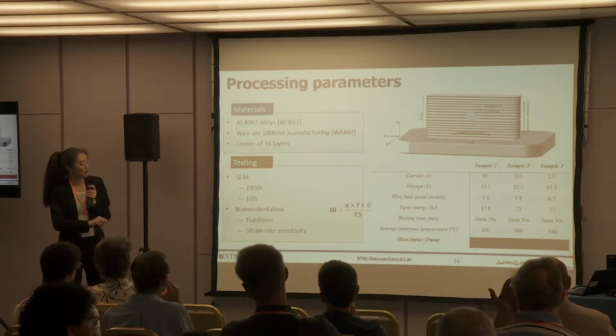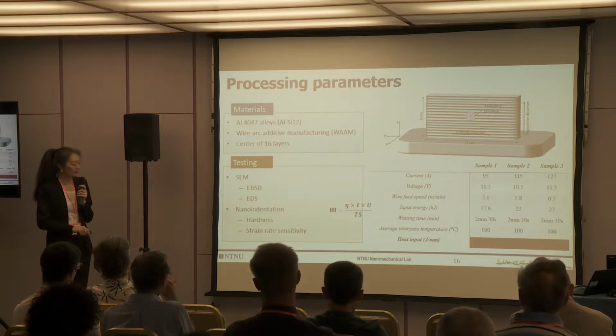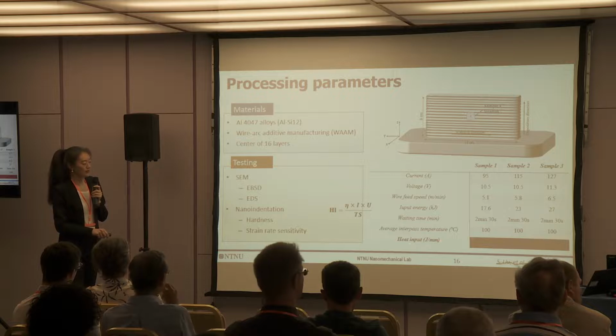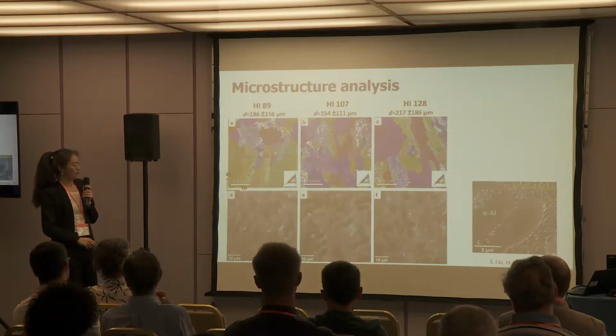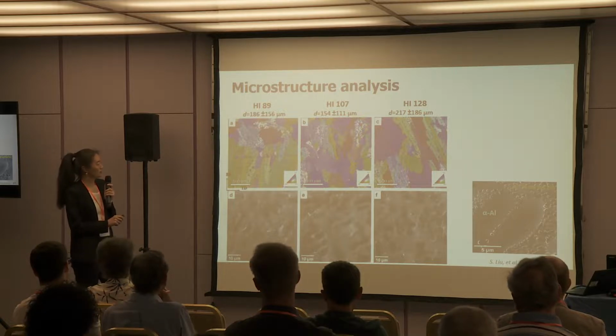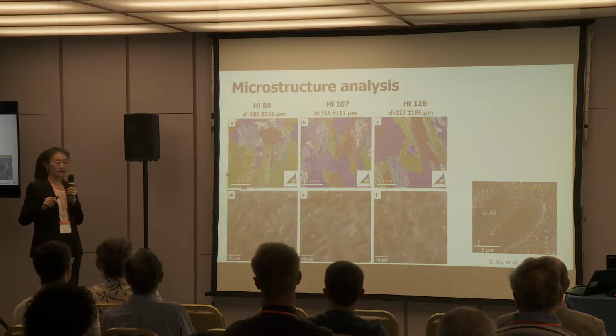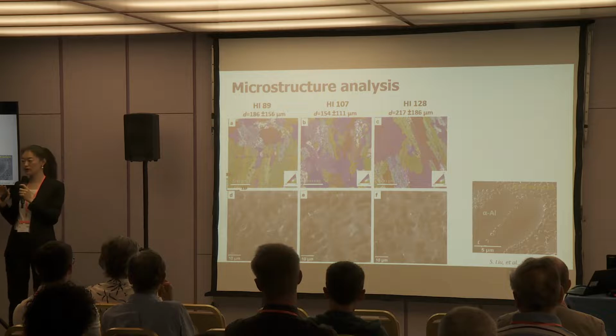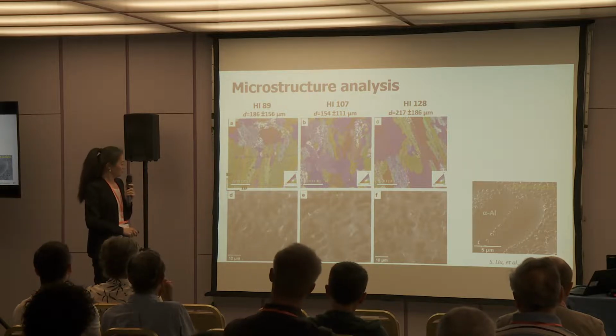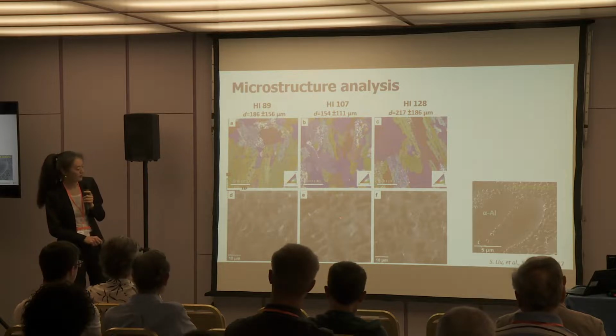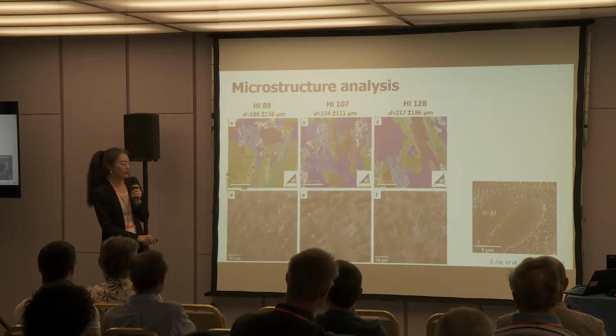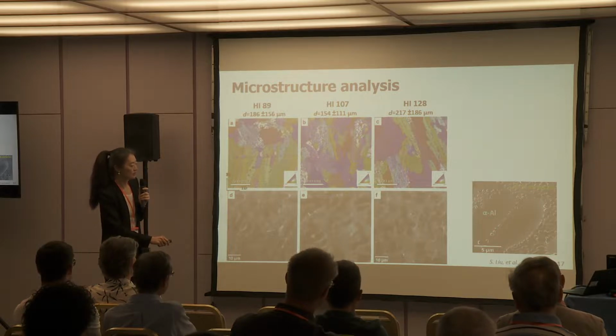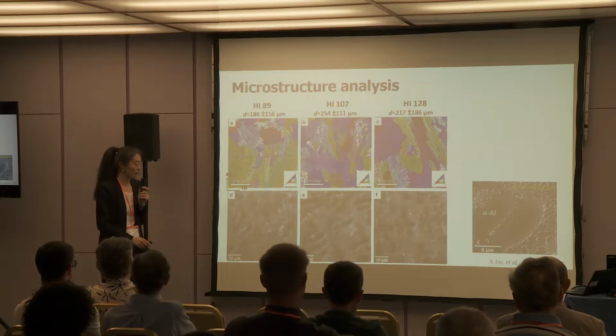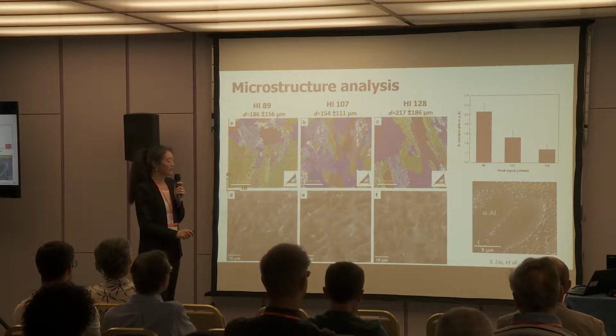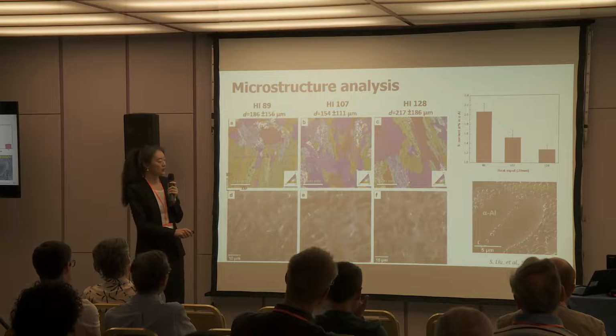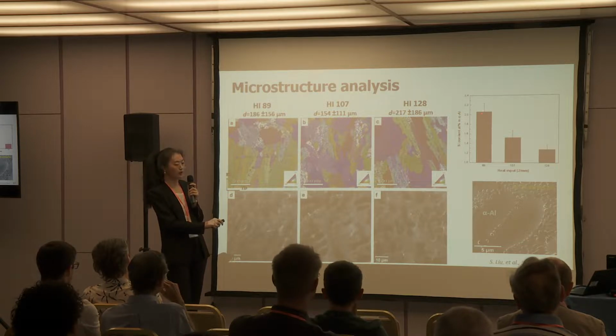Here are the printing parameters we used and the testing and characterization methods we are using. We focus mainly on this heat input change here. If we analyze the microstructure, we can see that the grain size changes with the heat input, but the grain size is really big. So by indentation, we are able to avoid any influence from the grain boundary and only test the grain interior. Then we see clearly two phases in the material. This dendrite structure is the primary aluminum, and also the eutectic aluminum silicon phase with those small silicon particles inside the grain. We also analyzed the silicon content in the primary aluminum and found an interesting trend: with increasing heat input, the silicon content in primary aluminum decreases quite significantly.